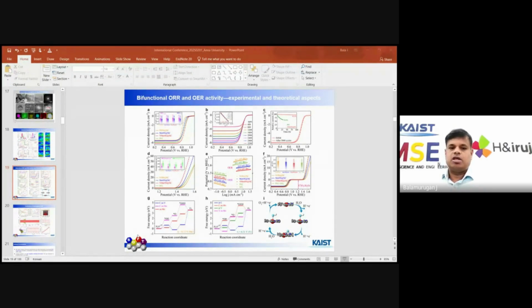And the DFT calculation also further proved that when we compare the different active sites, we can observe that molybdenum is the active site for ORR as well as OER. So you can see the mechanisms, how the oxygen is adsorbed and how it may be released during the rate determining steps of the ORR reactions.